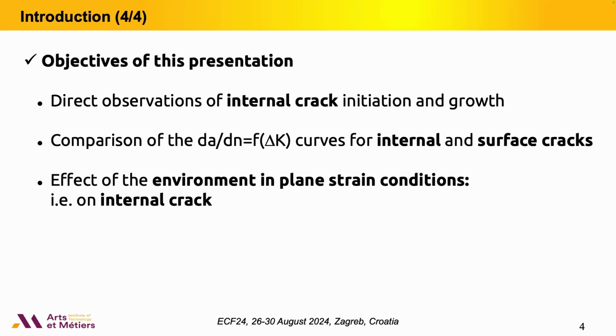So the objectives of the different works we have led with the PhD students were to answer the following questions. We would like to do direct observation of internal crack initiation and early crack growth in order to understand the mechanisms. And we would like to compare the kinetics of the crack at the surface and in the core of the specimen. The aim is, in fact, to study the effect of the environment on the crack growth under plane strain conditions, because in the literature, many authors explain that the criticality of internal defects and surface defects are different because the stress and strain states are different. At the surface, you are in plane stress, and in the material, plane strain.